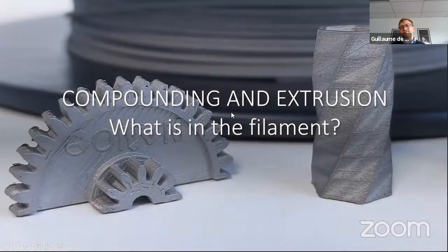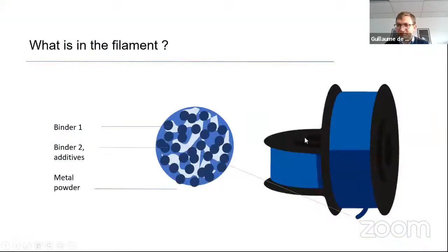So let's look into these several steps in details. The first step is compounding and extrusion. That's probably actually the most important step. That's what's going to give you the quality of the material. Here are a few keys to understand what's inside a filament and what makes it good or bad. If we zoom a bit on what's inside a spool of filament, you'll find, of course, some powder and usually a combination of at least two binders, sometimes more, a primary binder and a backbone, sometimes they're called, which will give different properties to the filament, some flexibility, some hardness. One of them might be soluble. So it's usually a combination of a few different binders. A lot of additives also, and of course, a lot of powder. And that's really the crucial point.